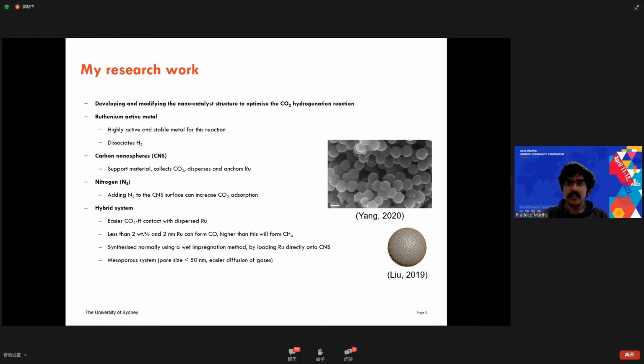Less than 2 weight percent and 2 nanometer ruthenium, as indicated in the literature, will form more carbon monoxide. Higher than this will form more methane.